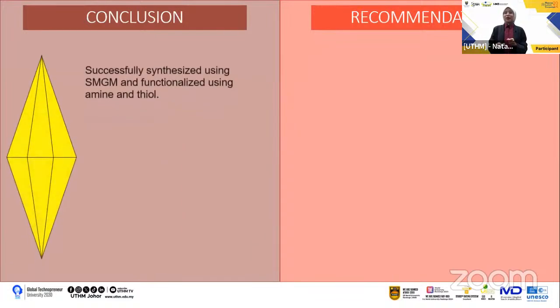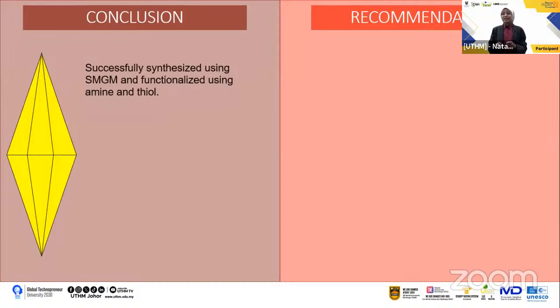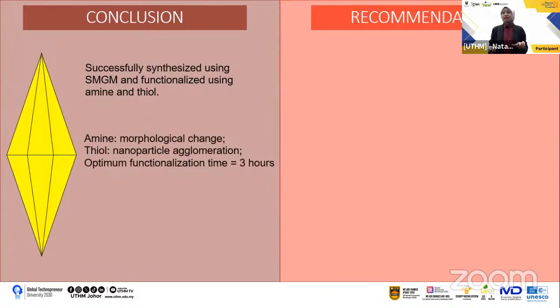Okay, now I will summarize the whole discussion. So overall, gold nanopyramids have been successfully synthesized and then functionalized using amine and thiol groups, where amine influences the morphological change, while thiol allows for the nanoparticle agglomeration. And when we proceed into the selectivity and stability testing, it is proven that the utilization of amine and thiol groups to modify our sensing material can improve the selectivity and stability performance of the plasmonic sensor when detecting glucose molecules.